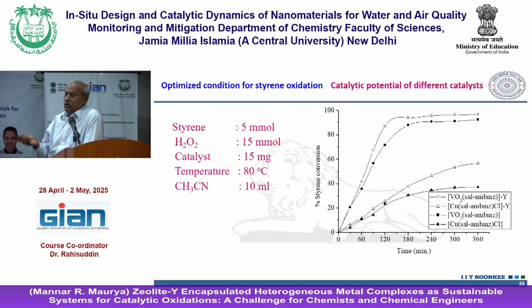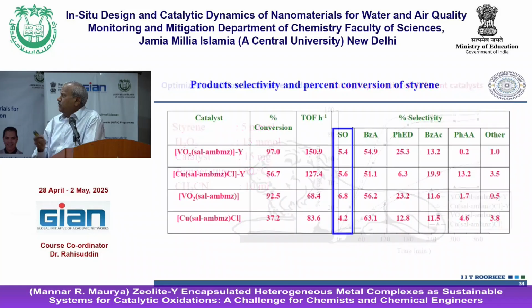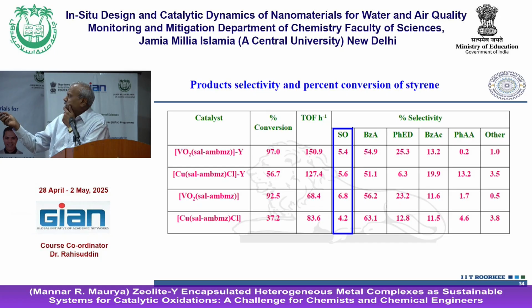However, when you compare zeolite and non-zeolite, you find a big difference in their catalytic potentials. This is the data. You see that as high as 97%, copper is giving only 56, 57%. And when you see the styrene oxide, not a very pleasant result, because it is converting into another product. What is maximum is coming like diphenyl ethanol, or even going to benzoic acid. Benzaldehyde is maximum, so that is expected.